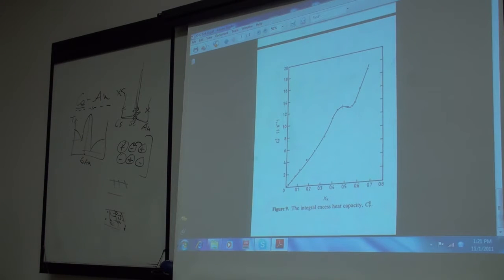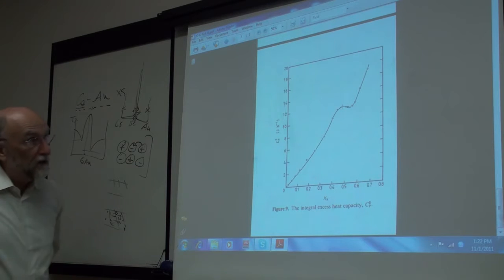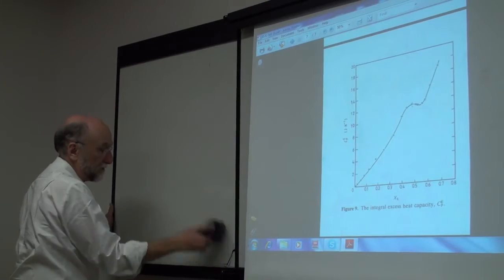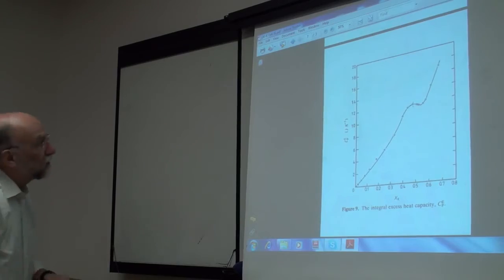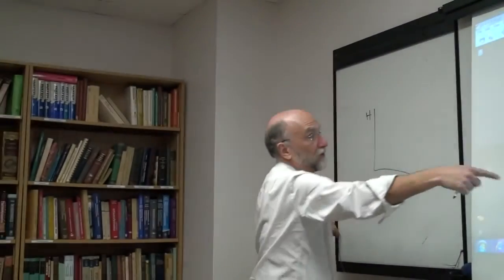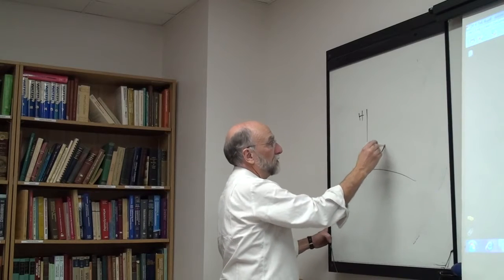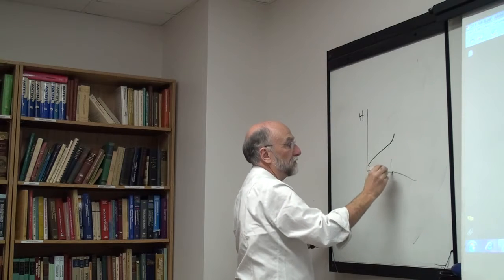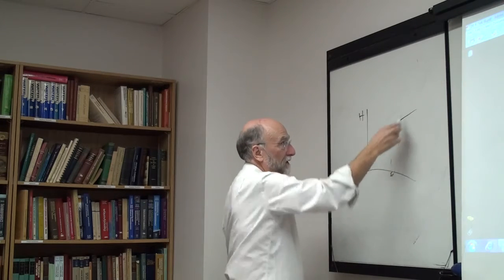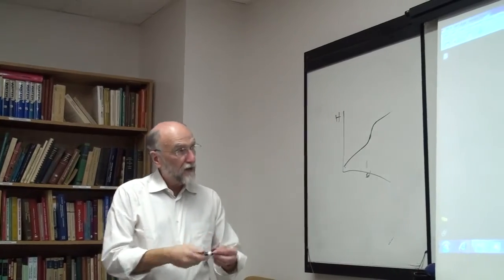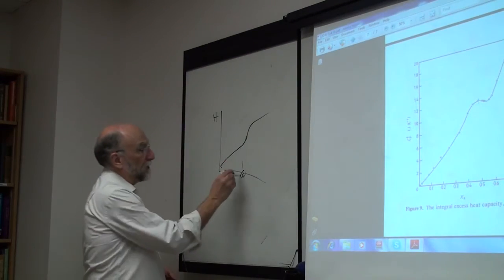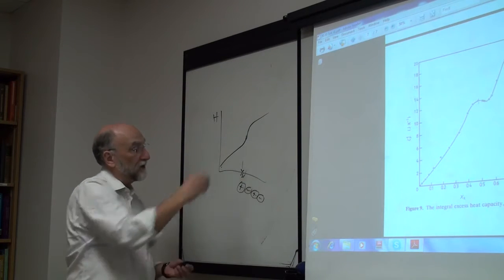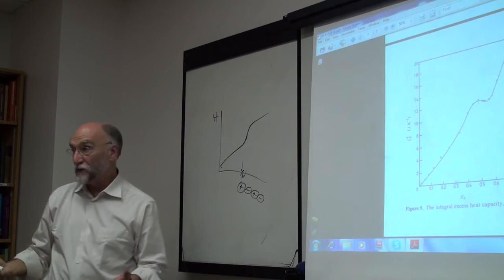Okay, so why do you get this excess heat capacity peak? This is another evidence for the ordering. Remember what excess heat capacity looks like if it's the slope of the enthalpy curve? So if we were to plot the enthalpy at this 50-50 composition, the enthalpy would kind of look like this. The enthalpy comes up, and then around the 50-50 there's a tendency here to increase. Basically what this means is at 50-50 you have ordering. But as you heat the ordered material, it tends to become disordered.